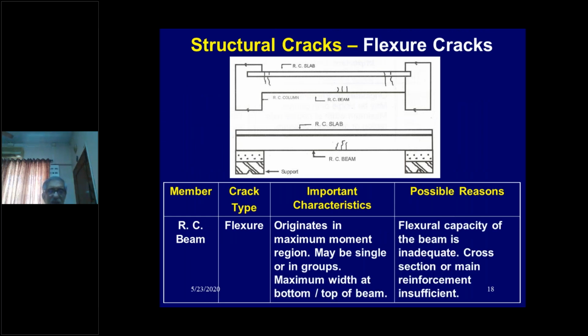Now we go into some structural cracks. The first and foremost is the flexural crack. This crack occurs in beams and sometimes even in slabs, originates in the maximum moment region, may be a single crack or a group of cracks, with maximum width at the top and bottom, like you see in the sketch here. If it's a fixed end moment, then it can occur at the top also. And if it's a free span, then it can occur at the bottom. Flexural capacity of the beam is inadequate, and cross section or main reinforcement insufficient. So that means these flexural cracks have occurred mainly due to the design.